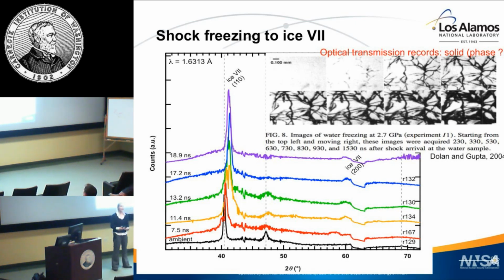I can also look at static compression, high temperature data, and compare their lattice parameters, essentially their equation of state, and pull out a pressure. I can also do that from the gold. And there's remarkable overlap, okay? So here we're seeing both the gold and the ice 7 tell me something like 5 to 7 GPa. Now this is really interesting because earlier data sets, shock compression,